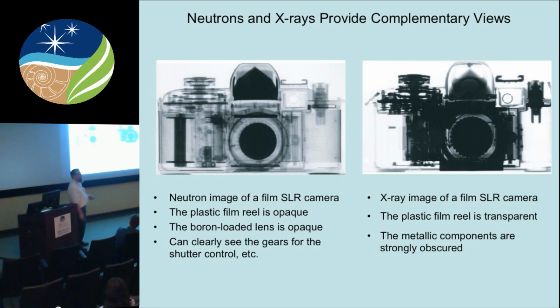This shows an old-fashioned film camera and just shows the difference between a neutron image, where, for instance, you can see things that are plastic, like the film roll, very well, and you can see a lot of the details back here in the operating material of the camera, whereas in an X-ray image, you really can't see the film roll hardly at all, and you get a lot of absorbance from all of the metal. These things work great in combination.